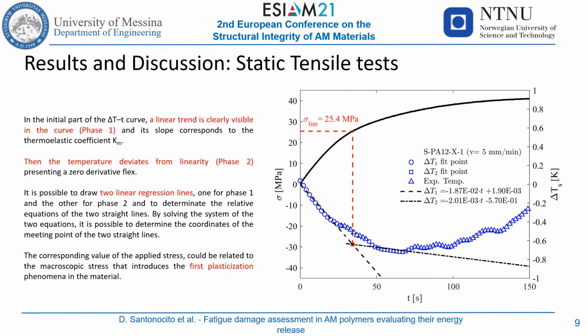In the initial part of the temperature-time curve, it is possible to clearly distinguish the linear trend of the temperature, then it deviates from the linearity, reaching a plateau region. Suddenly, it experiences a rapid increment. It is possible to draw two linear regression lines, the former for the first linear phase and the latter for the second phase, not taking into account the temperature values near the slope change.